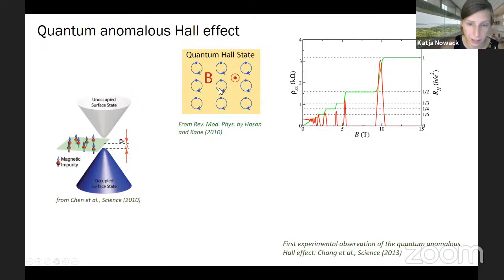And so all these electrons within go on these closed orbits, and then of course along the edges of the sample, which is not in the schematic, you get skipping orbits along the edge, and those give rise to highly quantized transport coefficients. So you can measure rho XX in your device, as well as the Hall resistance. The Hall resistance is highly quantized, and rho XX actually falls to 0. That's the key signature of the quantum Hall effect. Of course, there's a lot more to it, but for the sake of time, I keep it that simple.